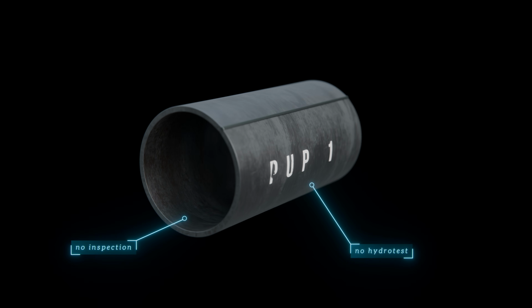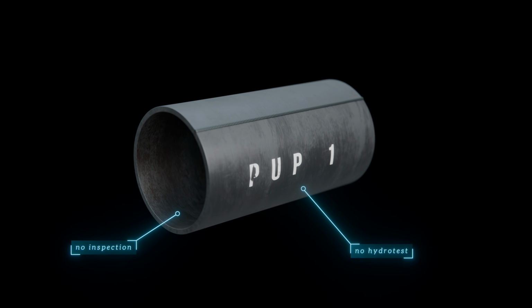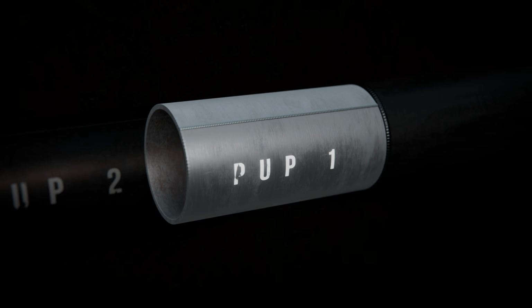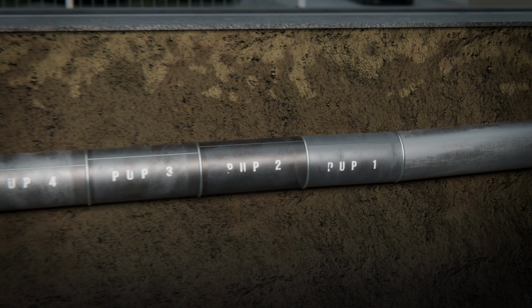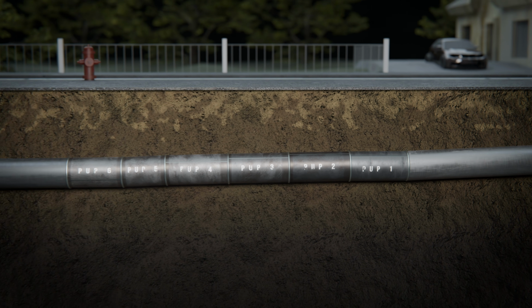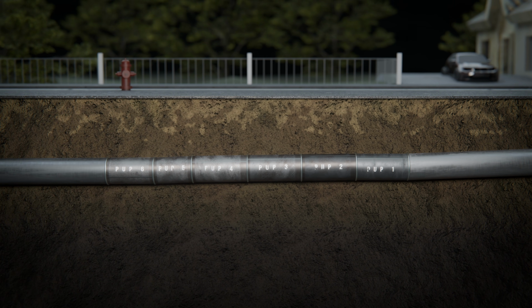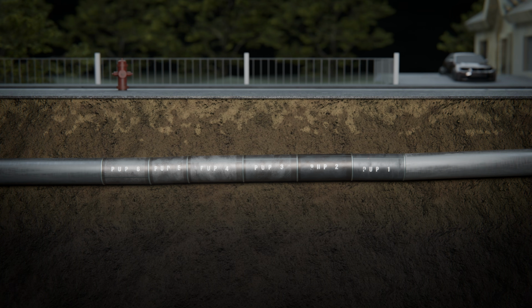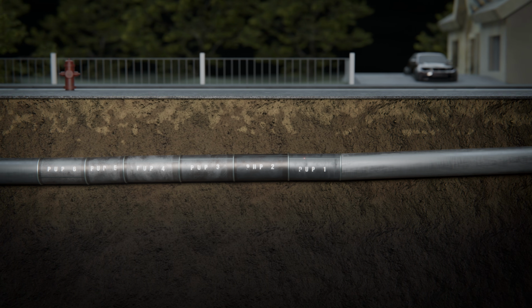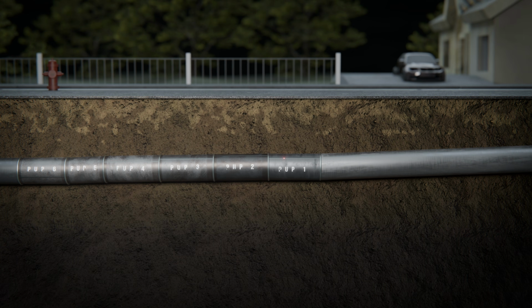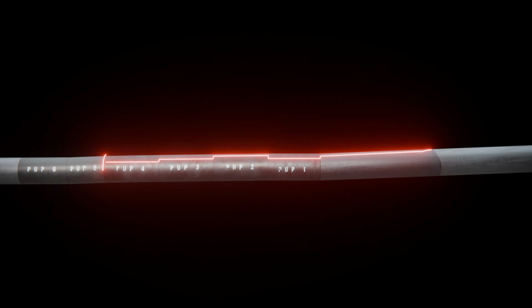It was built before the first inline inspection tools had even been developed, so it was never designed to be piggable. The route had tight bends and fittings that wouldn't let a pig through. All of this meant the seam weld defects were left to grow under the ground in San Bruno, getting longer with each pressure cycle until one eventually reached a critical length and fractured when the internal pressure increased momentarily during maintenance work at the upstream Milpitas terminal.